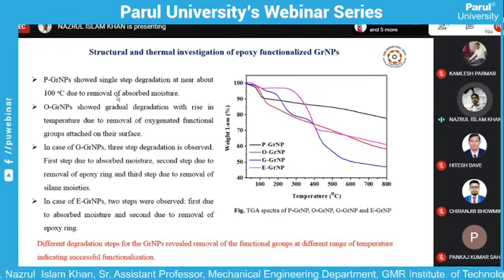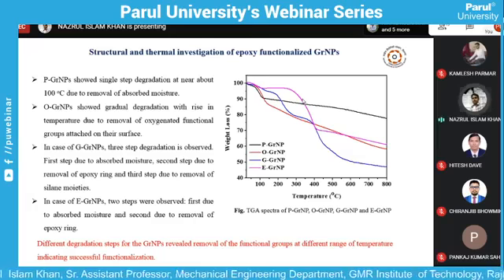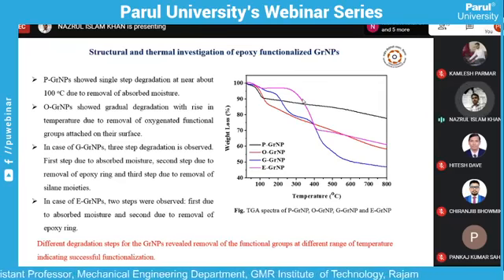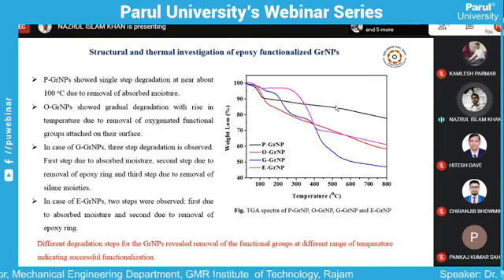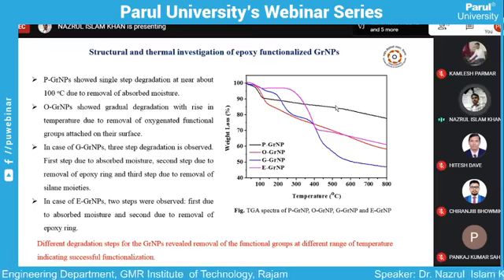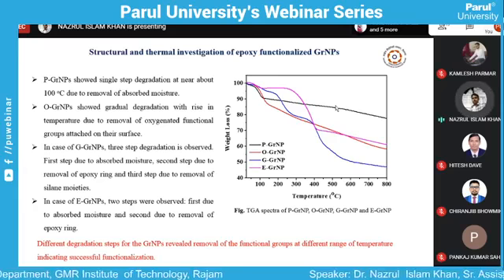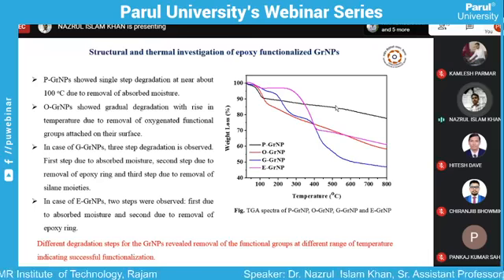Another example is thermogravimetric analysis, TGA analysis. This also can help determine whether successful functionalization has taken place or not. This black line shows the degradation. If you apply heat or temperature to any substance, the weight gets reduced due to evaporation of different materials. So if we record the weight loss with respect to rising temperature, we can determine at what temperature which components on the surface of the material have evaporated.